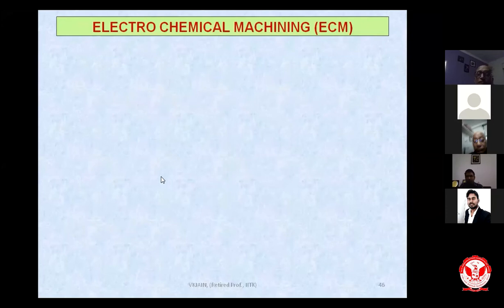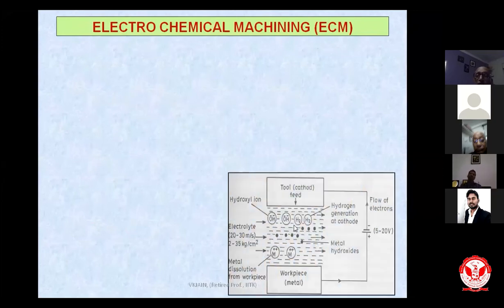Electrochemical micromachining, quickly I will explain, because time is not there. The working principle is simple. You know electroplating and Faraday's laws of electrolysis. We have the tool here, and the workpiece over here. The electrolyte is here, and it is electrically conducting. When you supply current to this arrangement, electrolysis takes place. As a result, workpiece material is dissolved, and if it is iron, ferrous hydroxide or ferric hydroxide is formed. The electrolyte moves out of the inter-electrode gap at reasonably good velocity, 20 to 30 meters per second. So you are able to create an approximately inverse replica of the tool on the workpiece surface. This is the principle used for electrochemical micromachining.